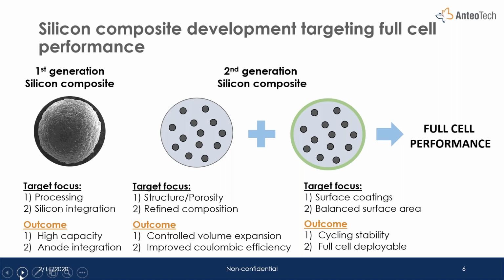And the anode integration aspect was already confirmed by our partners, as we already discussed in the quarterly report that came out last week. So to take the performance of these composite materials further, we have embarked on creating a second generation silicon composite material, where we are focusing quite heavily on making these materials usable in full cells by revisiting the structure, the porosity and the composition, and to balance out the higher surface area of the nanomaterials with surface coatings, all of which will help to control volume expansion, create improved coulombic efficiency, and consequently good cycling stability, which will then make these materials deployable in full cells, which is another term for the commercial batteries that are used in consumer electronics like phones or electric vehicle battery applications today.